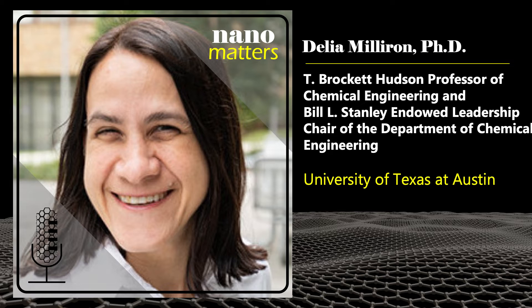Prototype lines for these sorts of things are usually meter-wide glass, and then you go up from there. To do the switching, we need to get the electronic charge in and out of this transparent thin film battery. We have transparent conductive layers on the glass that carry that charge all the way across the pane to the edge of the window, where metallic bars are hidden in the frame. Those can be hooked up to a control panel on the wall or even a central thermostat that can holistically manage your air conditioner, heater, ventilation, and windows together to optimize the energy performance of the building.